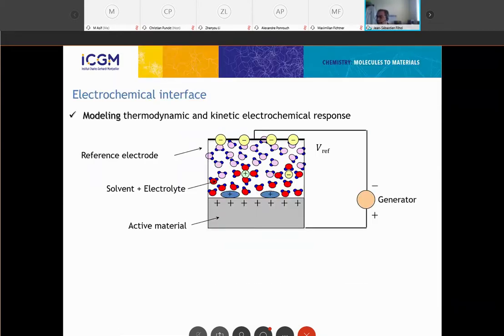First, I'm a theoretician of interface electrochemistry, and interface electrochemistry is quite complex because you have to compute the active materials, the double layer, and the electrolyte. Because of that, there's a lot of complexity, and one of the main complexities in these interfaces is the presence of surface charge and very strong electric fields that completely change the chemistry of the system.